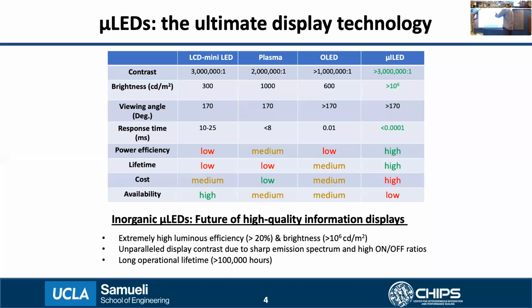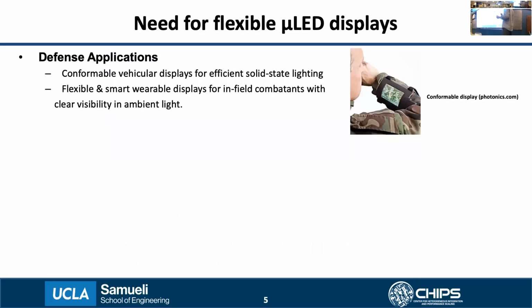In terms of lifetime, they can exceed more than 100,000 hours. Micro-LEDs have been shown to have power efficiencies, especially UV micro-LEDs, of more than 60%. Because of all these advantages of micro-LEDs, there's been a push both in industry and in academia to try to make displays using micro-LEDs.